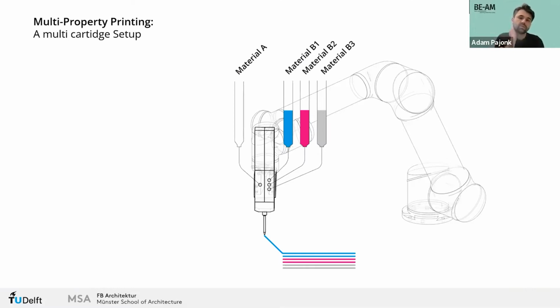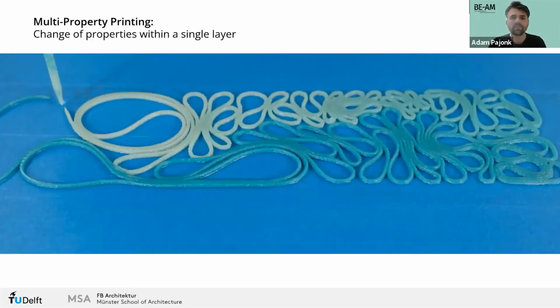So now coming back to the initial idea of enabling multi-property printing, we started to refine this process by not only implementing the two components that are needed to create this polyurethane, but adding more components, which then could be switched between throughout the print, in different sections of the printed objects. As you can see, for instance, you could just change from one mixture to another throughout the print of a single layer.